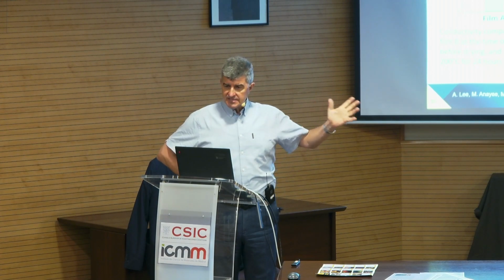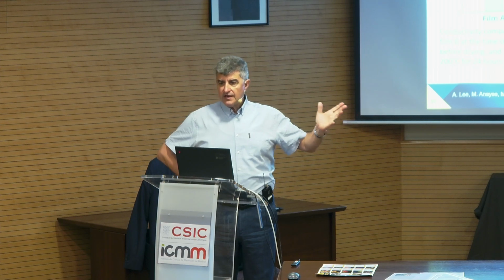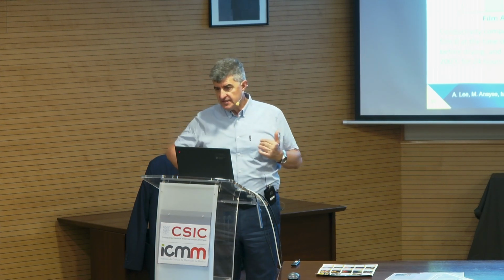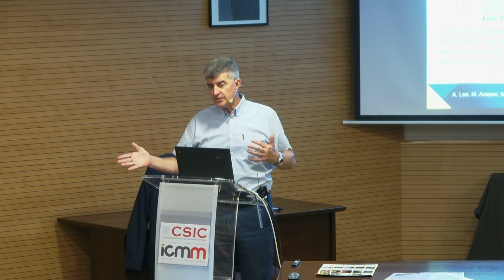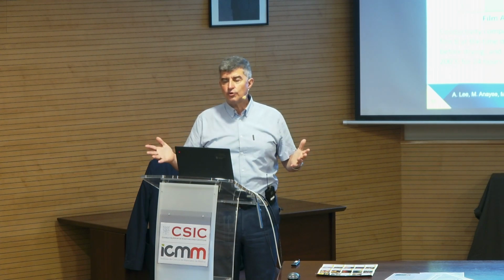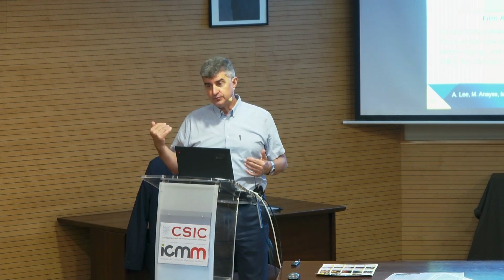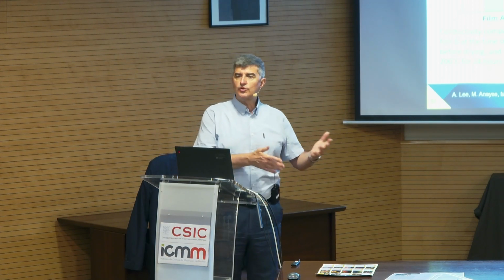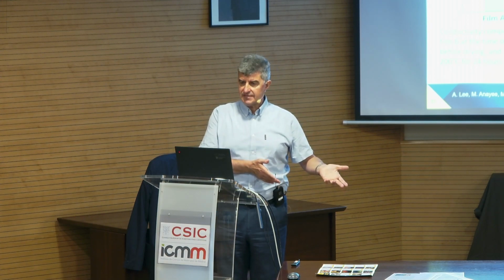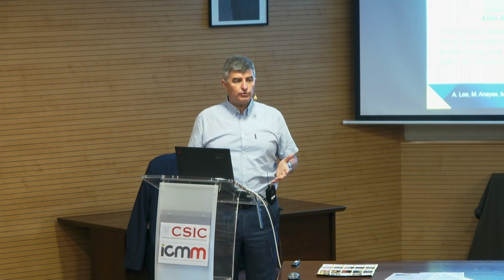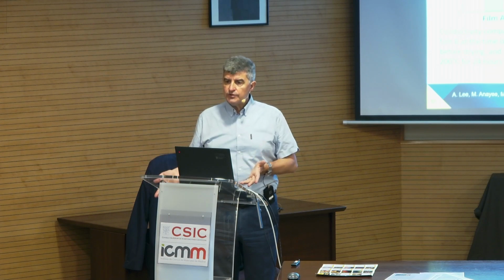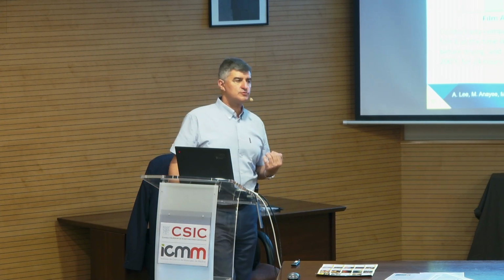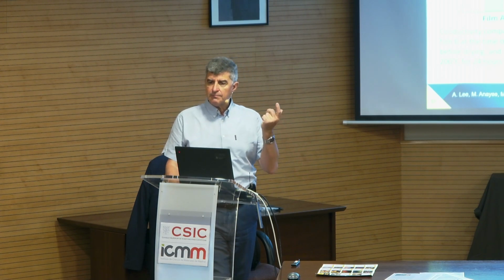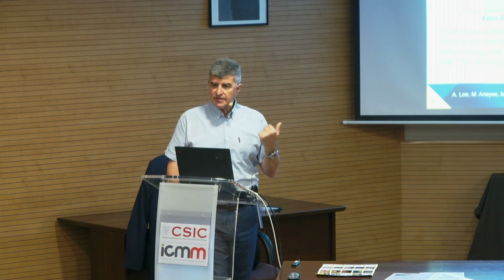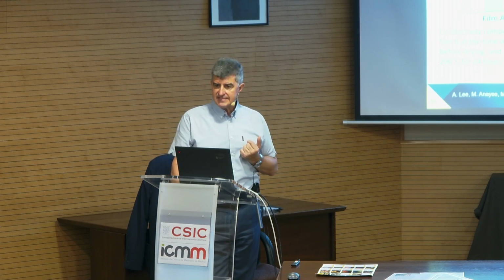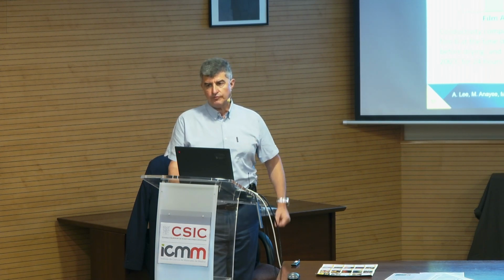However, keep in mind that the same variety of materials I mentioned will require much deeper understanding of how particle size and surface terminations will affect this. Can hydrolysis of fluorine on the surface lead to toxicity, inflammatory response? Can soluble chromium or vanadium compounds from those MXenes cause toxicity? So again, you cannot talk universally about it. Those are materials you need to study. But materials used so far for biomedical application, primarily titanium carbides and niobium carbides for thermal therapy, have been quite extensively studied, not showing signs of toxicity so far.